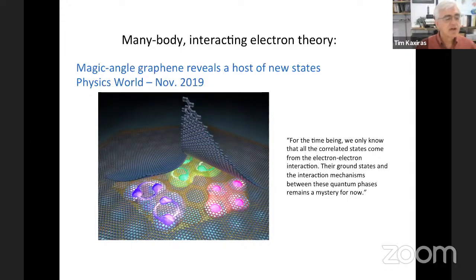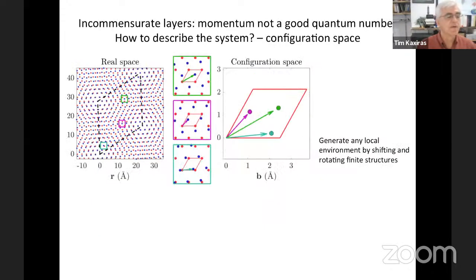And early on, it was realized that very simple bands cannot account for the symmetries that the system requires in order to produce this description. So we have been working very hard to produce a very accurate description of twisted bilayers, in general of incommensurate layers, because if you put two layers on top of each other at an arbitrary angle, you have an incommensurate system. Once you have an incommensurate system, the momentum is not a good quantum number anymore. So the question is how to describe the system.